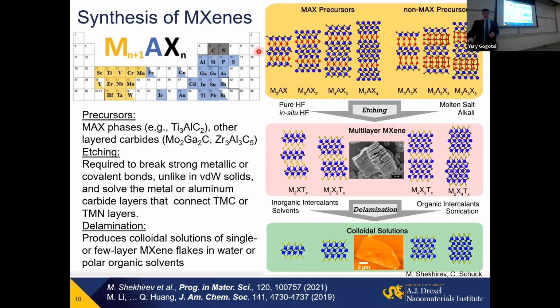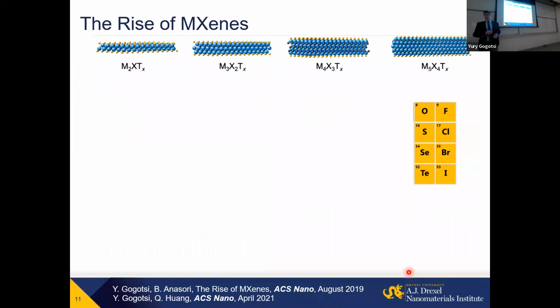But after you etch them, there is this surface termination coming. We mark them by the letter T, often, like terminations here. And now you have particles which look largely like thermally expanded graphite or vermiculite clay, for example. We have seen SEM pictures of those. And now there are weak van der Waals bonds between the layers. You can delaminate them by intercalation or other methods and get single layer particles from those materials.